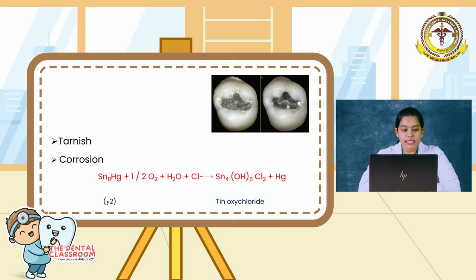Other disadvantages of amalgam are that it has the tendency to undergo tarnish and corrosion. Tarnish is the surface discoloration on a metallic surface without any loss of structure. In case of low copper alloys, the gamma phase is responsible for surface tarnish, while in high copper alloy, the copper rich phases eta and silver copper eutectic.